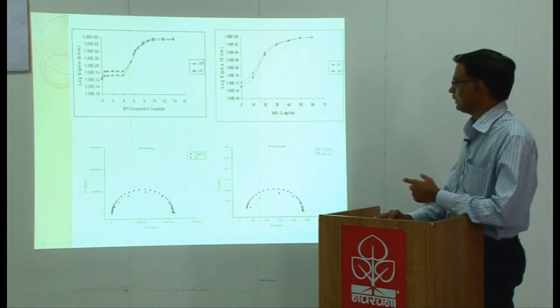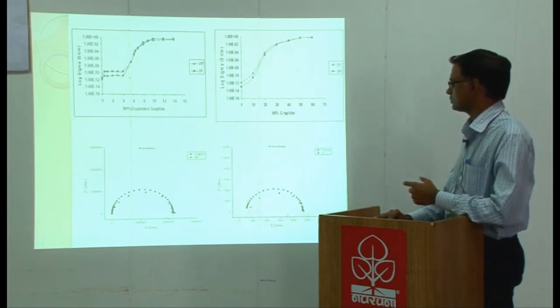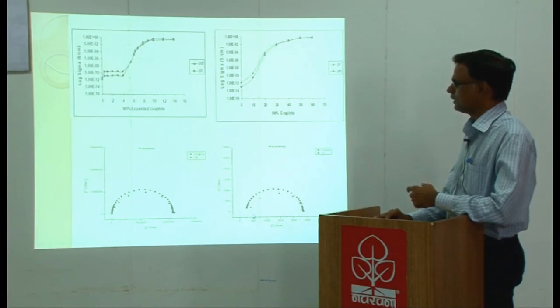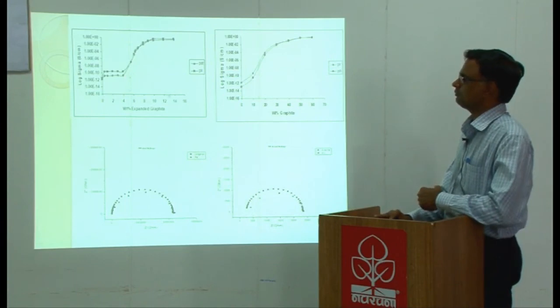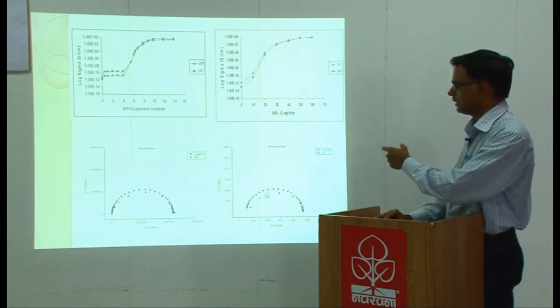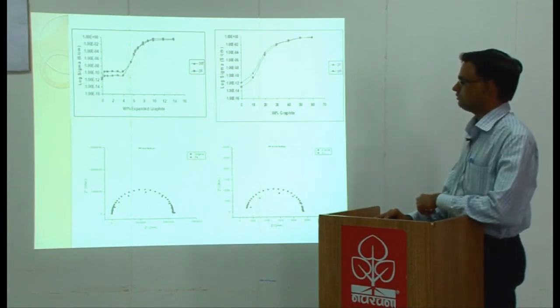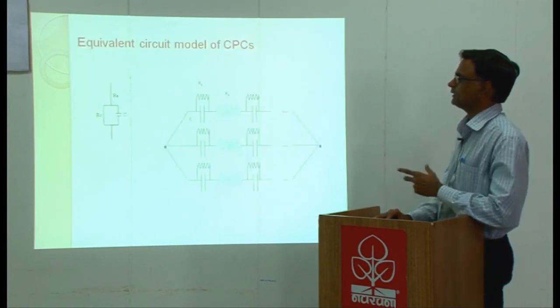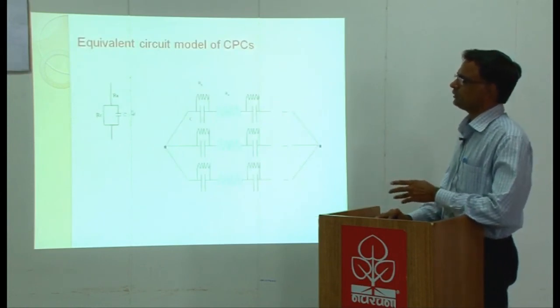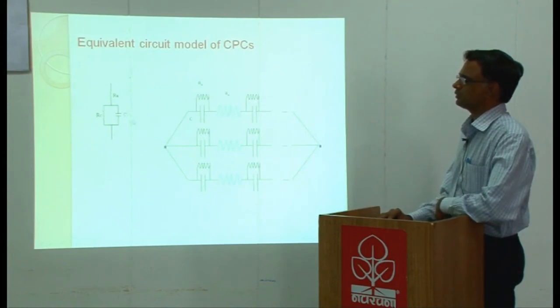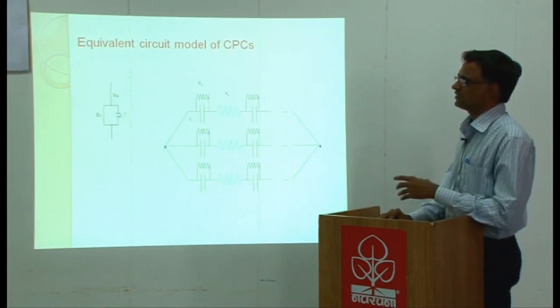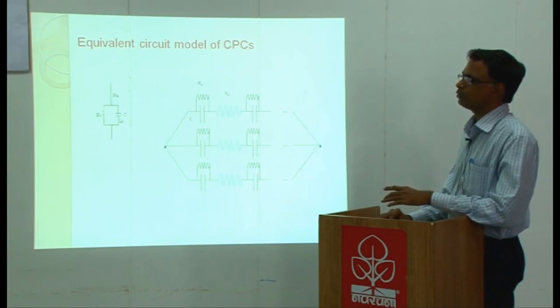When you have higher loading, the diameter becomes less. You can see the value over here. And what it is used for: we know the same result from DC conductivity, but additionally this gives us interfacial capacitance details. This is the typical equivalent circuit model of conducting polymer composites, where CPCs can be modeled as parallel combinations